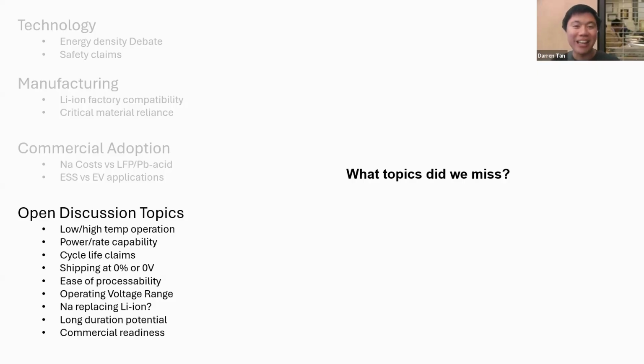And some people ask, can I ship it at 0 volt, right? We have tried it. It works, but there are consequences to it. We noticed that the sodium-ion batteries that are shipped or stored at 0 volts don't perform as well as those that are shipped or stored at 0%. But it's not because of the copper foil. What happened is post-formation, SEI and CEI is formed on both electrodes. And those are only stable within a certain electrochemical window. And if you leave that window by going to 0 volts, then they break down. So you basically reform the cell again when you cycle it after being stored at 0 volt. But 0% is not a problem.